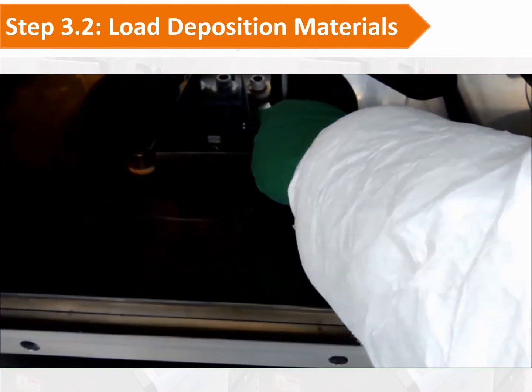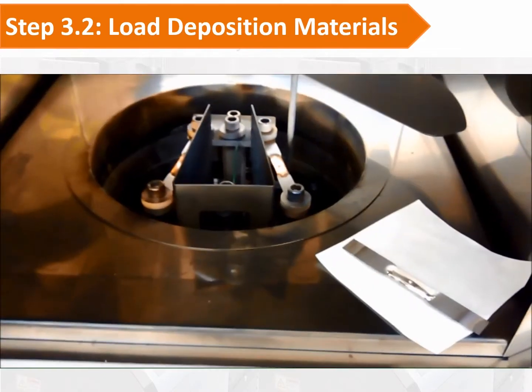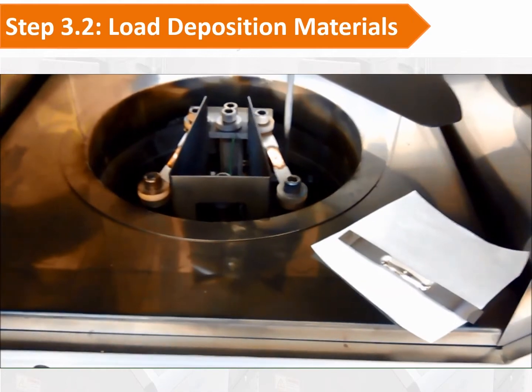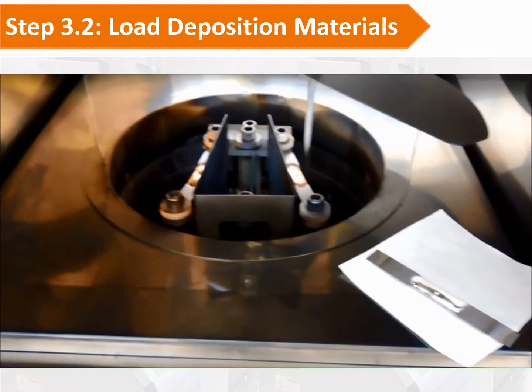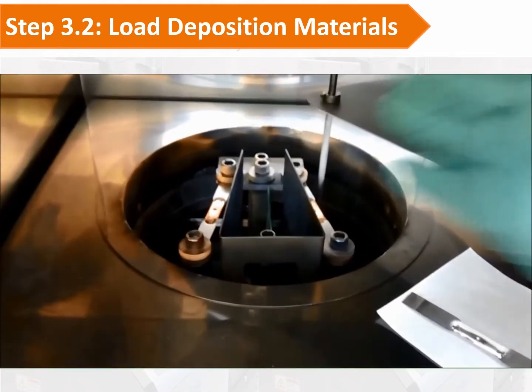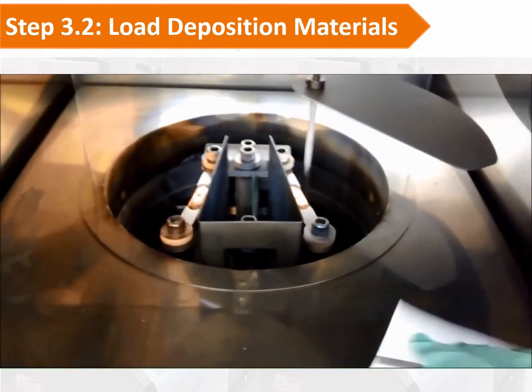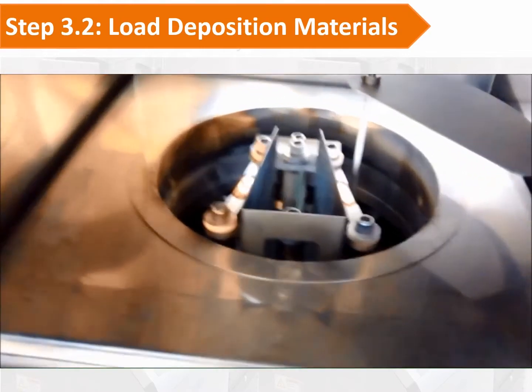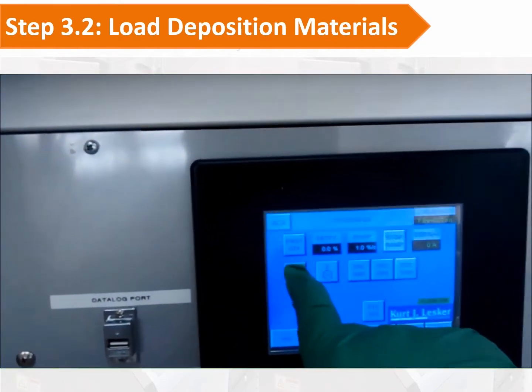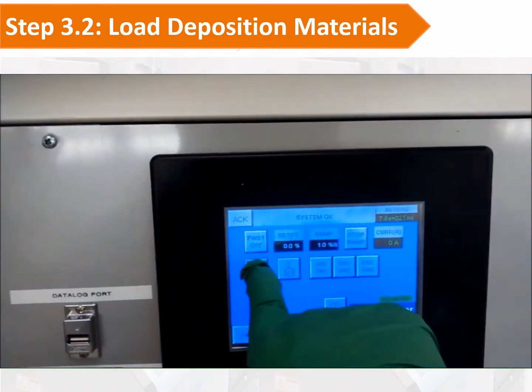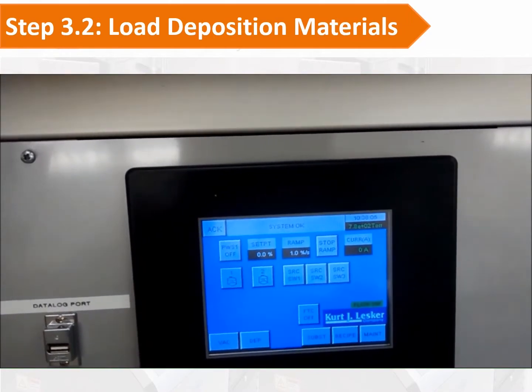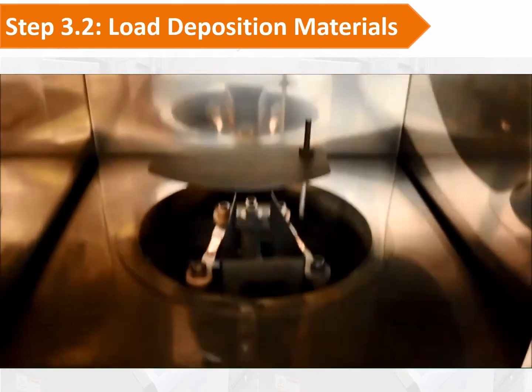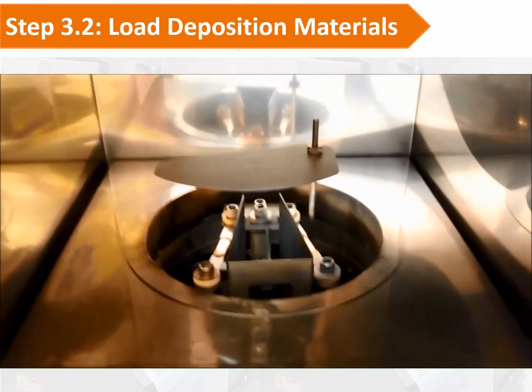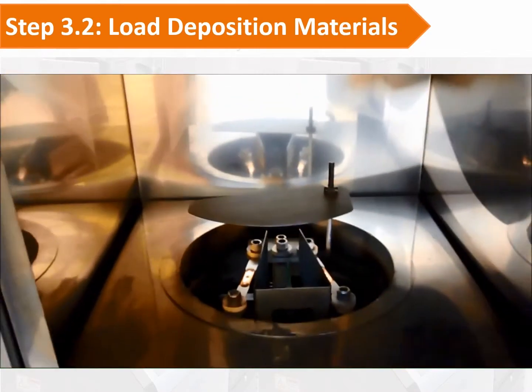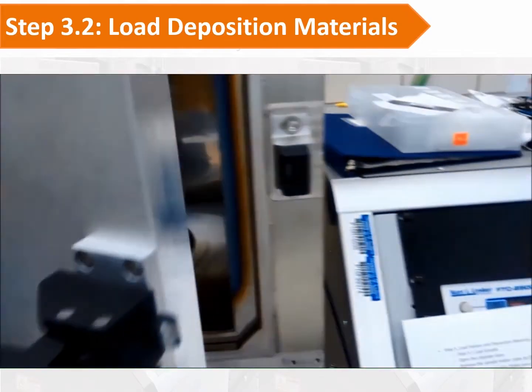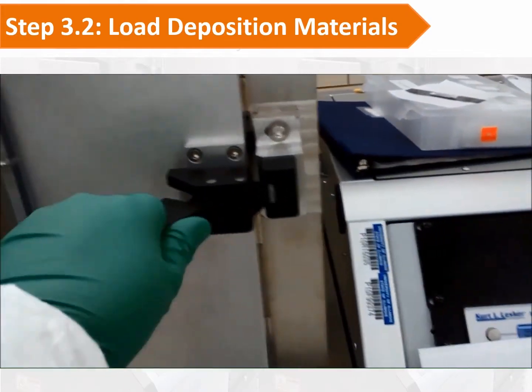This is because during your process, you will heat up these bolts, and if you tighten them too much, the bolts will become brittle and may break prematurely. And then we grab the silver bolts out, and now we are ready to close the shutter. Now you can check that the shutter is closed. And then we need to carefully close and lock the chamber door.